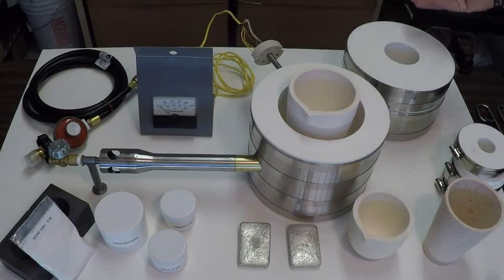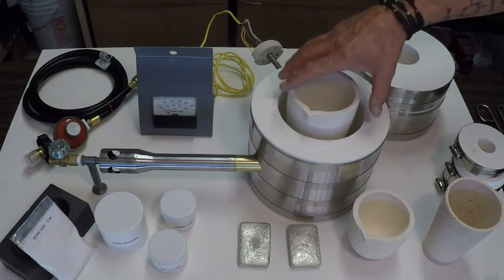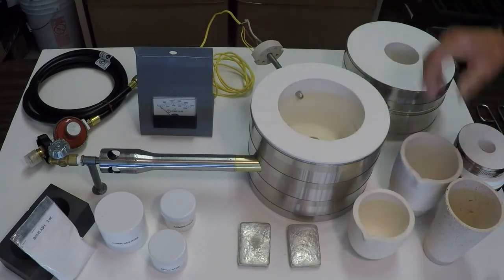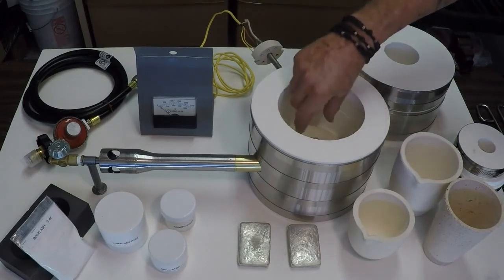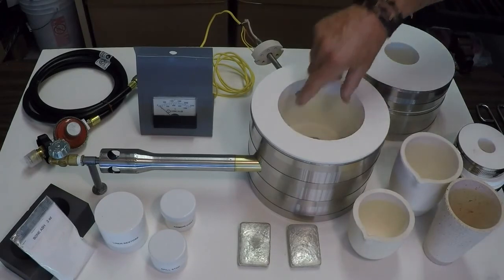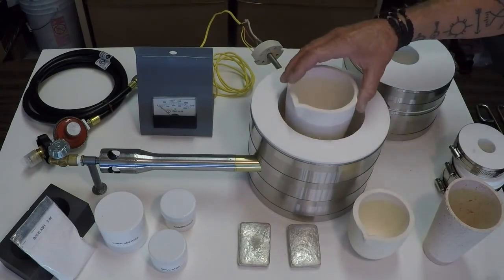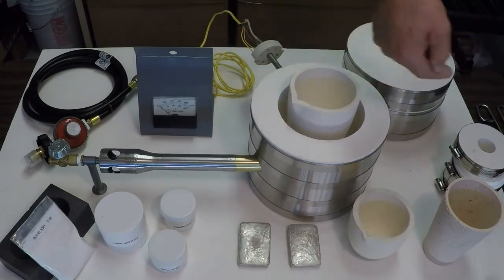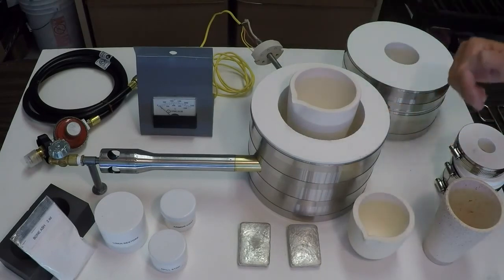With this design where the top and base of the body come apart, inside is a pedestal - a ceramic cone 12 pedestal, I call it. What that does is keep your crucible up out of the direct blast of the burner, so one side of your crucible doesn't get hot and the other side remain cold and crack.